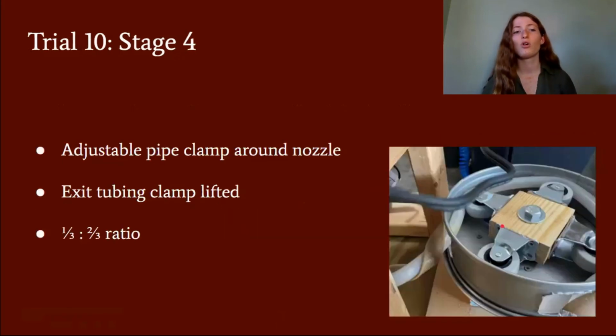So I decided to up the sulfur in the ratio. And I also lifted up the exit tubing clamp to try to push down the tubing that was actually inside the pump. And I switched out the pipe clamp by the nozzle because I had noticed some air. However, this also did not work because immediately when I poured through the sulfur concrete, it started to flow through just by gravity alone. So it started to solidify in this straight stretch here before I could even start with the pump.